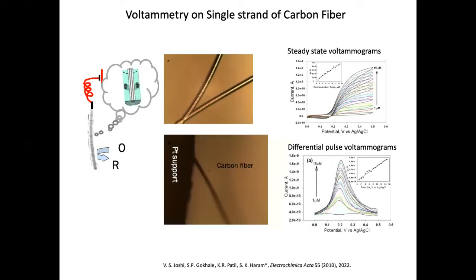For that, you need a very small, micron-size electrode to have minimum invasion. That's why these electrodes were developed. So now we have this single strand of carbon fiber, which is the electrode. You can see this small fiber electrode attached to the platinum support, and now we can measure the dopamine concentration.